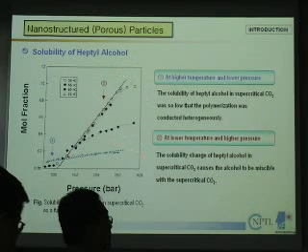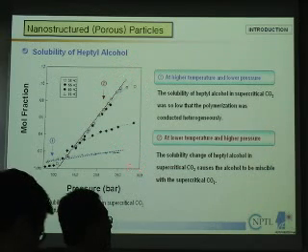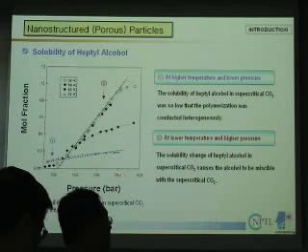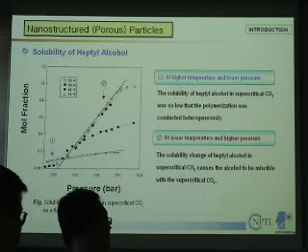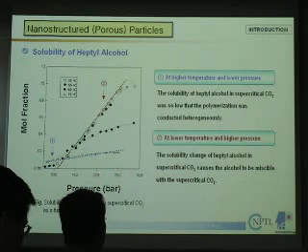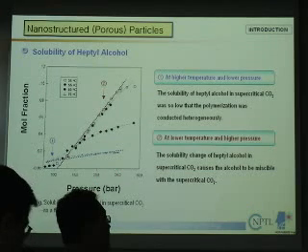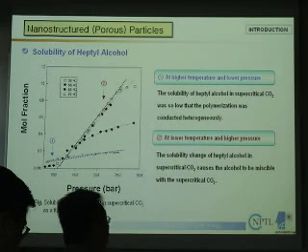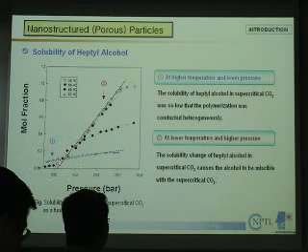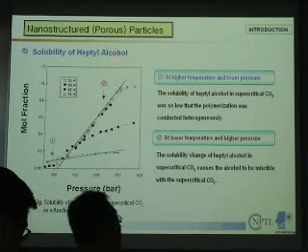That means in the initial stage, you need to have some kind of solvent that can act as the second solvent to control the solubility in the continuous supercritical CO2. So in the initial stage, you use these conditions. Number one, we chose heptyl alcohol for our system.